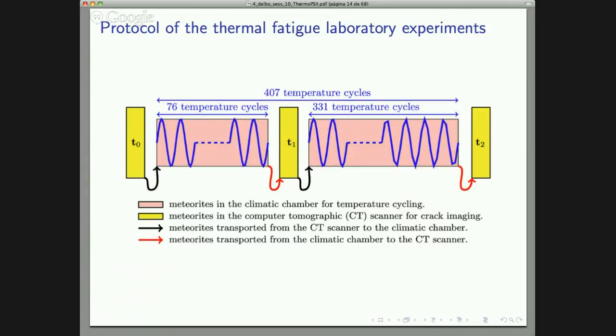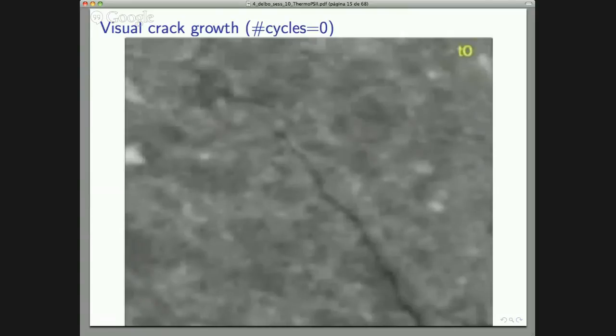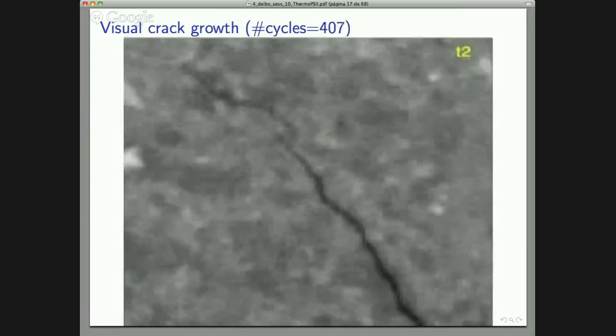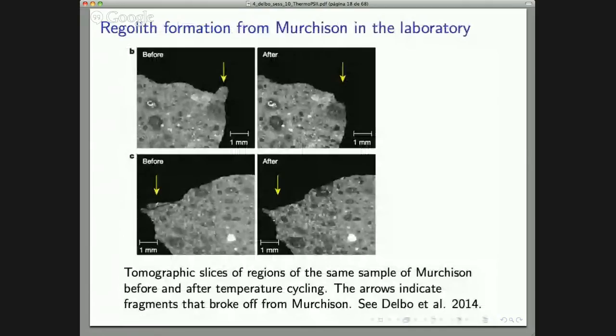And here you see an example. This is just a slice of a tomography, and you see a pre-existing crack on the Murchison at T0, so before, 1 week after, and 1 month and a week after. So you see that something happened. We even formed some regolith from the Murchison, not from the other meteorite, which is much harder. They're like chips that fell off of Murchison due to thermal cycling.